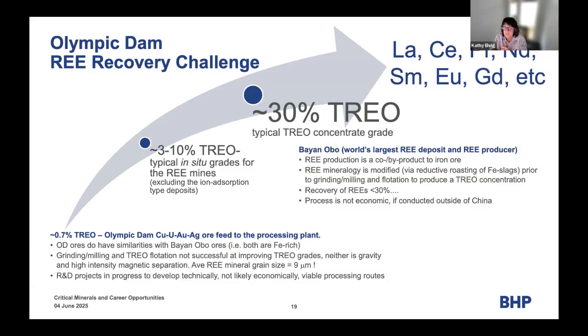The recovery of their rare earths is less than 30%, the best I can glean out of the literature. And because this is such an energy intensive process, dealing with all those extra slags, you think it's uneconomic if that process is done outside of China because it's so energy intensive. But it still provides us an idea to say, well, let's look at what we have going on at Olympic Dam. We actually have a smelter, and at the end of the process, our electric furnace is a reductive roast. We actually do grow monazite inside of that, but it's very, very small. So by looking at how they're producing it elsewhere, we can ask how that will apply back at our site. So we try to learn as much as possible from other producers.